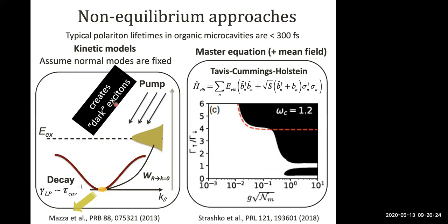Okay, so we had those slides a few slides ago on the work from David Snoke's group and the work from Daniele Sanvitto's group on equilibrium BEC physics. In organic systems, we're typically very far from this regime. The reason is that most organic microcavities that have been used for condensation have very short polariton lifetimes, on the order of 300 femtoseconds or less. I believe the best demonstration has a lifetime of 1 picosecond. These timescales are much shorter than typical relaxation and thermalization times in these systems, so the dynamics of these polariton condensates are out of equilibrium.